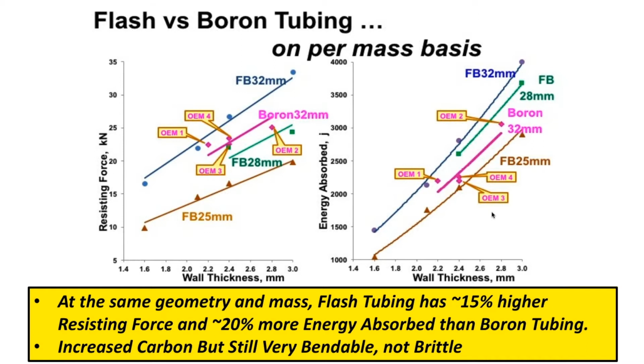I like to look at this resisting force chart at the wall thickness of 2.4 millimeters because there's a nice abundance of data. And you can see that the flash bainite 32 millimeters has about 15% higher resisting force at the same diameter and same wall thickness as the boron 32 millimeters. If you go over to the right-hand side, what happens is similar at 2.4 millimeters, looking at the energy absorbed situation. The flash bainite actually has about 20 to 25% higher energy absorption, same diameter, same wall thickness.